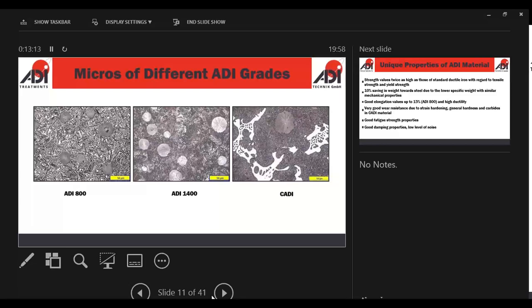And on the right-hand side, we have the carbidic ADI. This is a grade where we actually purposely add chromium and moly into the melt. A lot of foundries aren't appreciative of that because it's not what they do. So normally we're limited to the foundries that will make carbidic ADI. There are other ways of making carbidic ADI that don't involve using chromium moly. That's generally through the inoculation process to try and form iron-based carbides in the melt, like a chill carbide, and then use that as a carbide to get the additional wear resistance into the casting.